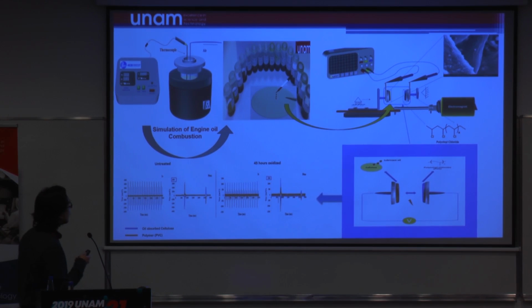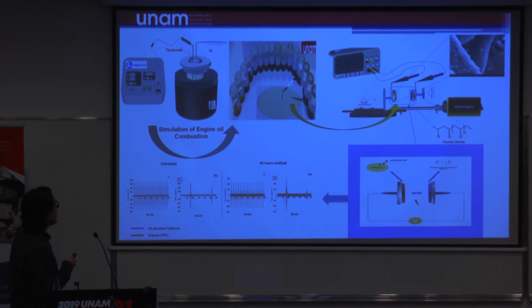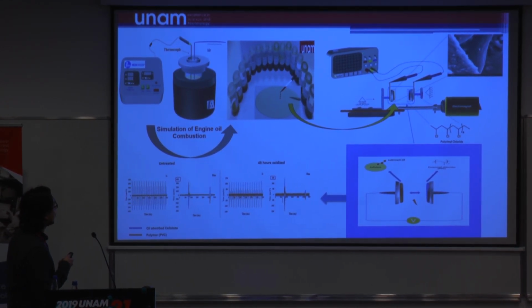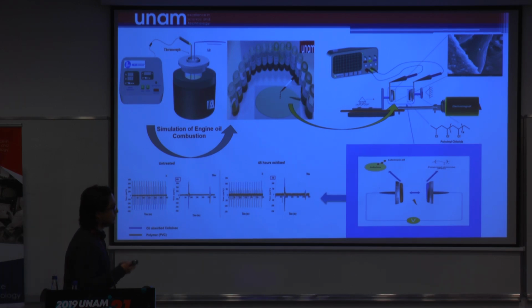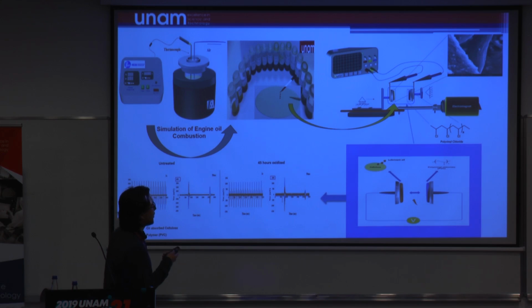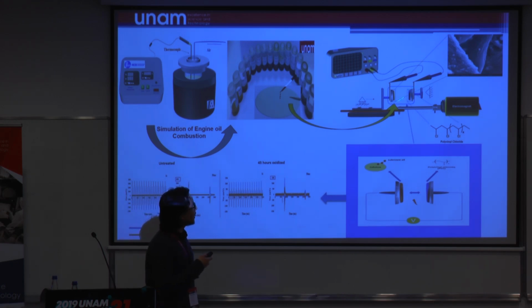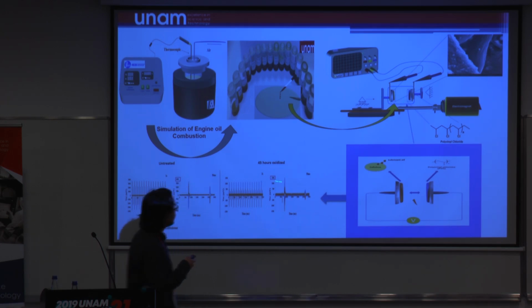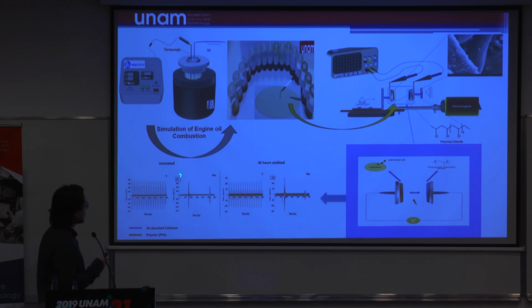Initially, we prepared our samples with a simulation of the engine oil combustion system, and we prepared different samples by picking them up at different time intervals and absorbing them onto cellulose paper. By using the contact separation mode of the polymer and the oil-absorbed cellulose, we got different signals in terms of the different oxidation times.